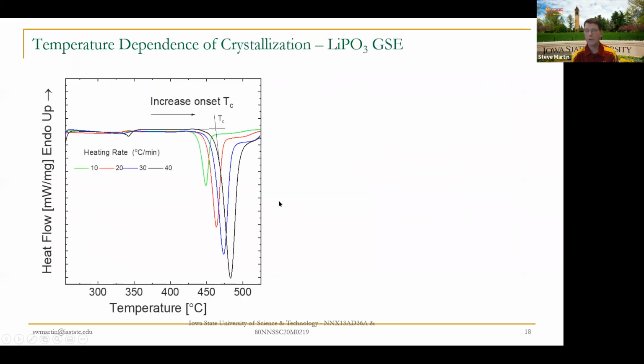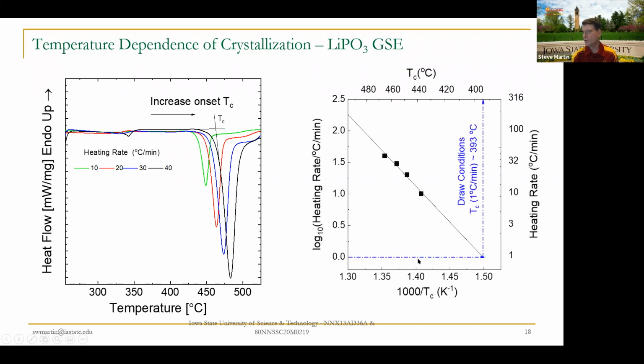But we also want to study the crystallization. Where does the glass crystallize? So we do a series of what are called differential scanning calorimetry. We just measure the heat capacity. We see a nice change at the glass transition temperature here, and then we see crystallization events. We do that as a series of heating rates, and then we do a simple Arrhenius plot.